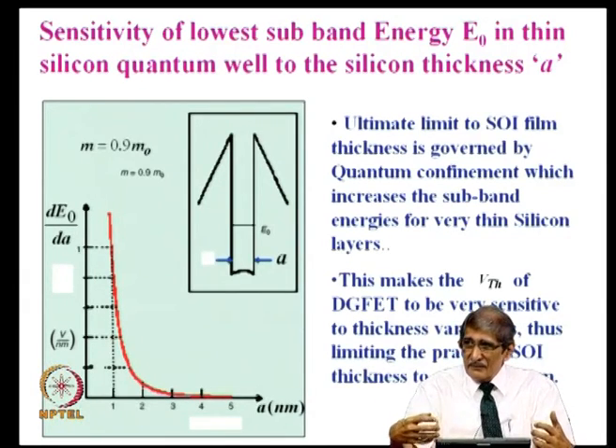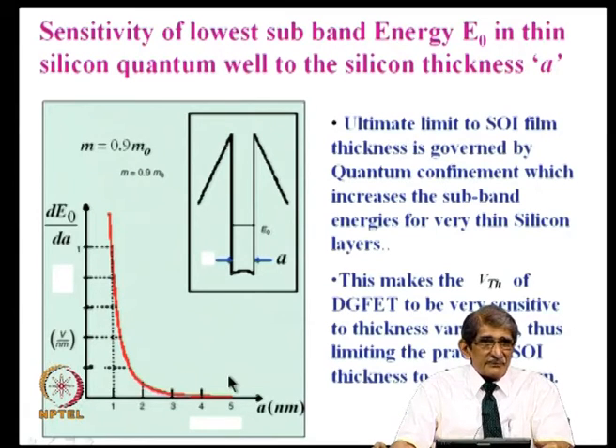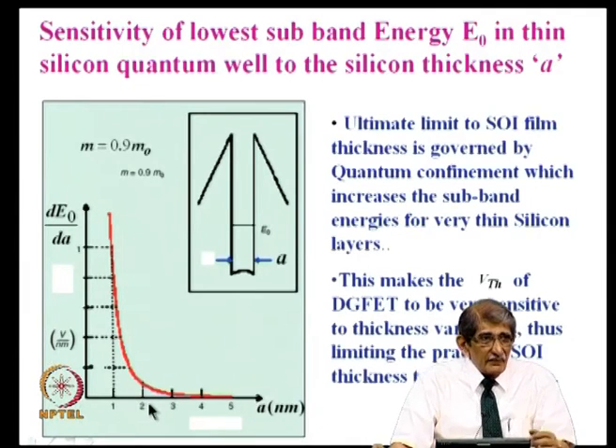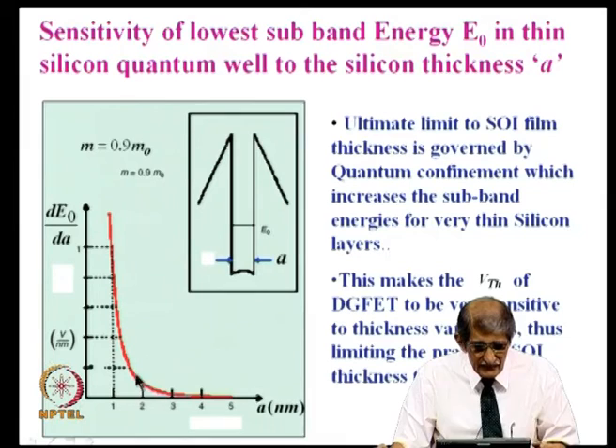4 inch, that is okay, 100 millimeter diameter SOI layer, or if you want to talk of 8 inch across that entire wafer, it is very difficult to get uniformity of 3 nanometer. There may be 3 nanometer, 2.5, 2.8 like that at least, then you can see it goes up like that, threshold voltage goes up. If there is 2 nanometer if you choose, then if it becomes 1 nanometer, you can see there is tremendous amount of change in the threshold voltage. So, your entire digital circuit will be malfunctioning there, analog circuit no hope. Okay. So, the uniformity in the threshold voltage will be affected if you go to thinner.